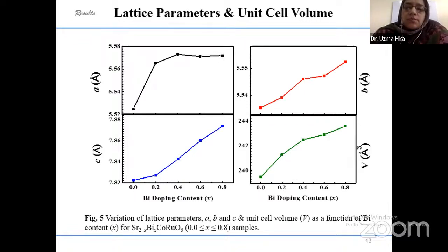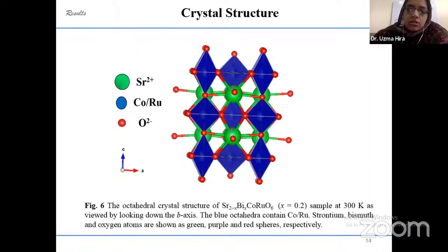One possible reason is that in the case of bismuth, we have a lone pair of electrons, which could result in distortion and expansion of the unit cell. This is the crystal structure we have drawn in VESTA software using the XRD data. You can see this green is the strontium site, and the tinge of purple indicates that bismuth is going into the crystal structure at the strontium site, which is basically the A site of the perovskite material.